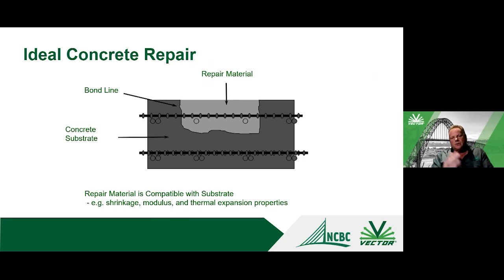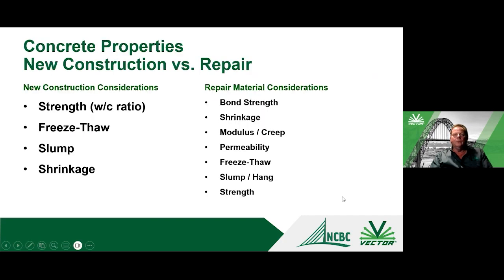So starting off, repair material selection can be important, because instead of compressive strength, we want materials that are more compatible from a repair standpoint, which may be things such as the shrinkage of the repair material or modulus or thermal expansion capabilities. Bond strength is also something we normally don't think about in new construction. So the repair material considerations can be different than what you consider for new construction.